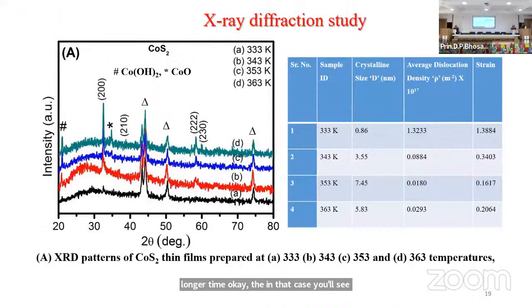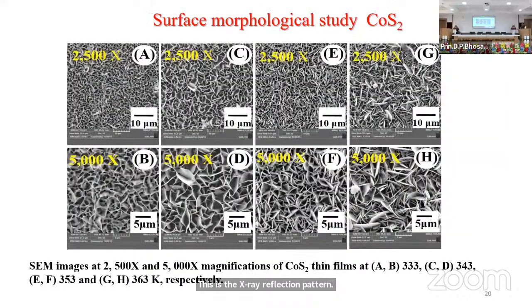this is the X-ray diffraction pattern, of course. Look at the morphology. Now, why are we looking for such types of morphologies? Because this will form an anode or a cathode. And when we put the electrolyte in between, the electrolyte can go inside this part. If it is a compact one, if there are no holes, it's very uniform, a compact film is formed, then the electrolyte will not be able to go inside. But by making such types of films, we are increasing their surface area.